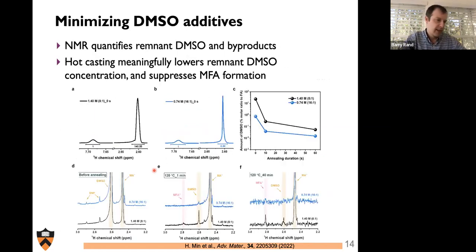But what we did do was we used NMR, and I'll come back to this right at the end of the talk just to bookend it, to quantify what's left in the film, both before and after annealing. So you take your as cast film and then you wash it into an NMR vial cuvette, and you can then quantify the content of that film. And what we did was we first looked into quantifying the amount of DMSO that's left. And we did this by integrating and setting to 1 the formamidinium peak and comparing that to the integral of our remnant DMSO peak, shown here at around 2.6 parts per million.